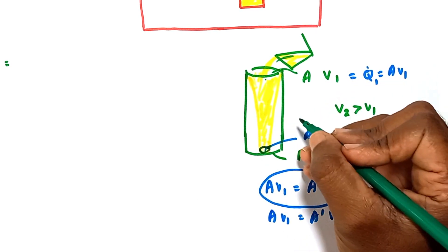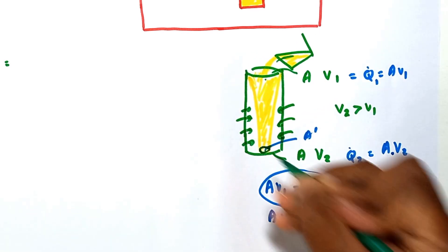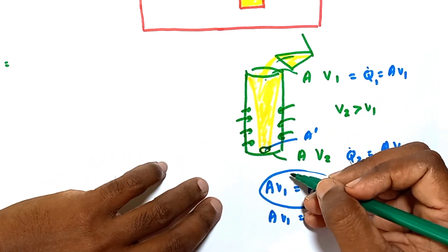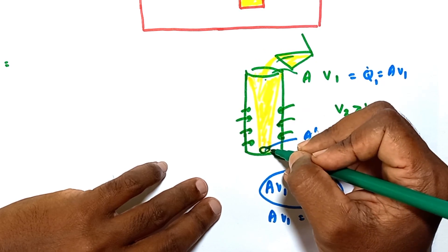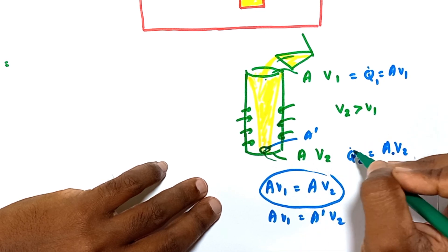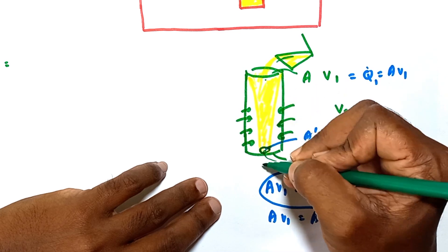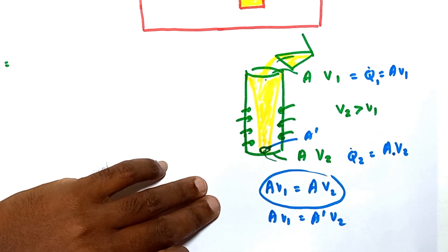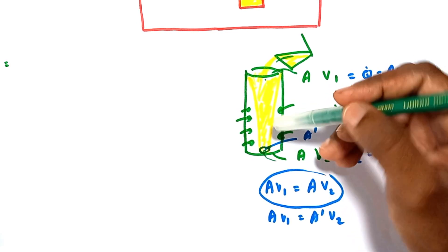When the flow narrows, an air vacuum forms in the surrounding area of the sprue. The surrounding air gets sucked into this area. This air then mixes into the flowing molten metal, and there is a high possibility of air entering the casting. This causes casting defects. Without giving the proper conical shape, product defects may occur due to air trapped inside the casting. This phenomenon is called aspiration.